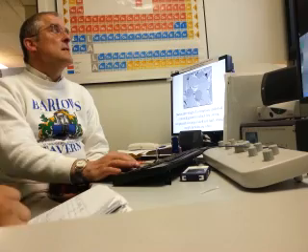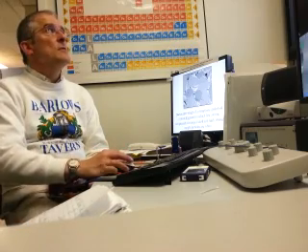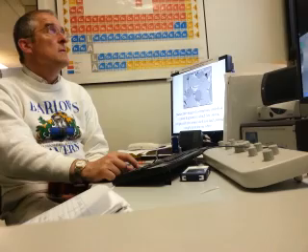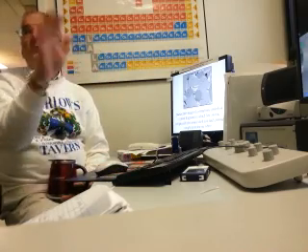All right, and these are just gold particles on the surface. This is your backscatter of a rock. The different atomic weights cause different numbers of backscatters to be generated, so that's why you have different intensities there of the rocks. In a secondary, this would all look like a uniform gray.